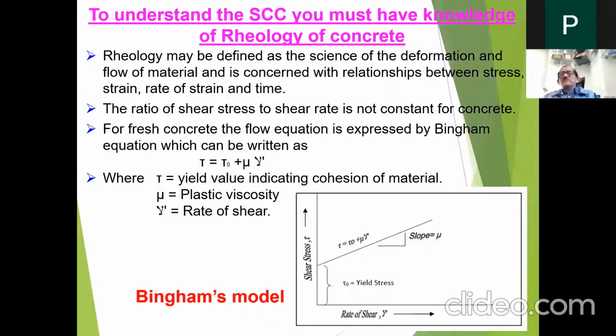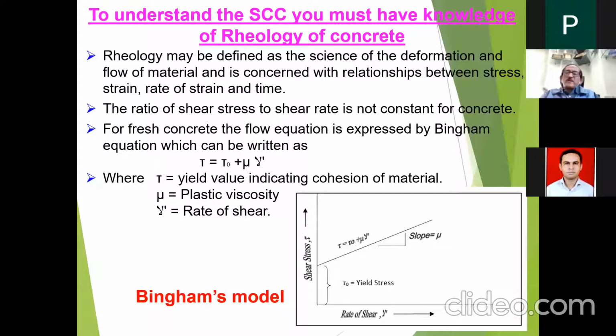For fresh concrete, the flow equation is expressed by Bingham's equation, which is tau equals tau 0 plus mu into gamma. So what is this? The relation between the rate of shear and the shear stress is defined by the slope mu, and there is a fixed yield stress. Yield stress is fixed because when you take the slump, you see the concrete in a heap, and when you try to displace it, you require some initial force, which is the value of yield stress tau 0, and then the concrete will go on flowing. So initially it has some value, and this is a property we call thixotropic. So concrete is not an ideal liquid, but a thixotropic material.